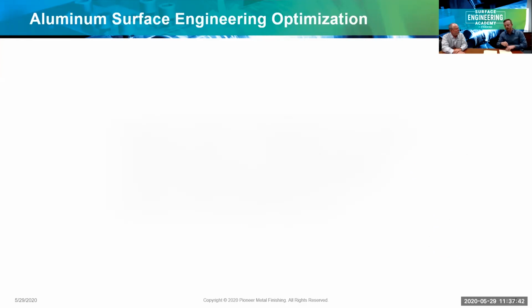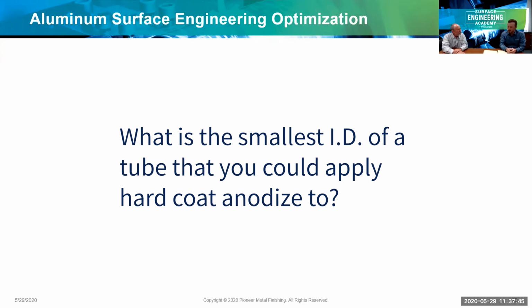Next question would be, what's the smallest ID of a tube that you could apply hard coat anodize to? Inside diameter. Yep. Well, in general, it's a combination of not only the diameter, but the depth. And the rule of thumb is that we don't want to see a diameter that's less than 25% of the depth. So if you start getting a very long, thin blind hole, then you're going to have issues with solution flowing and the electricity flowing. But normally, in general, when you get beyond less than a quarter inch, you don't want to see a hole that's longer than 3 inches.